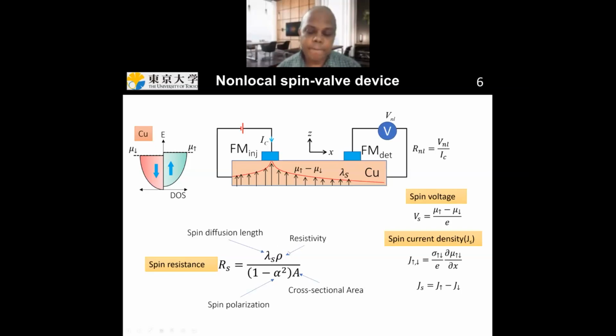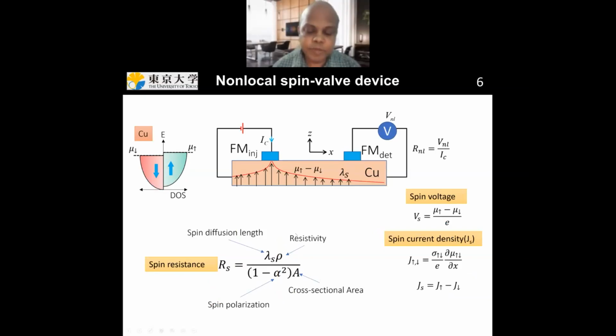Okay. In general, resistivity depends upon the relaxation times and the effective mass. I want to know that. Yeah, it depends on the spin relaxation time, and because it has spin, the lambda s depends on the spin relaxation time and the diffusion constant, and the rho depends on the electrical transport relaxation time. So you can say that it depends on two relaxation times. One is the relaxation time of charge scattering events, the other is the spin relaxation time. Electrical resistivity depends only on your scattering time tau, the momentum scattering time.